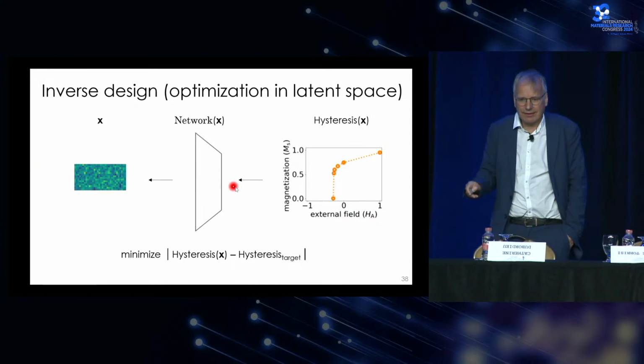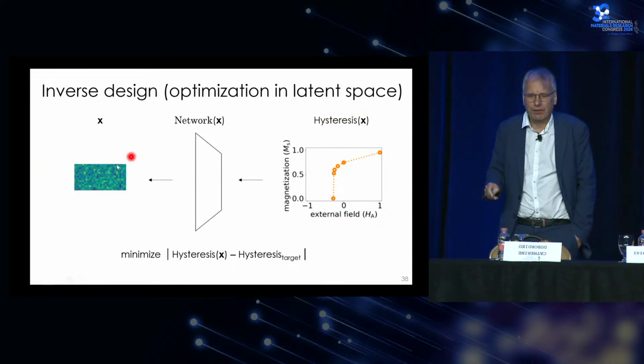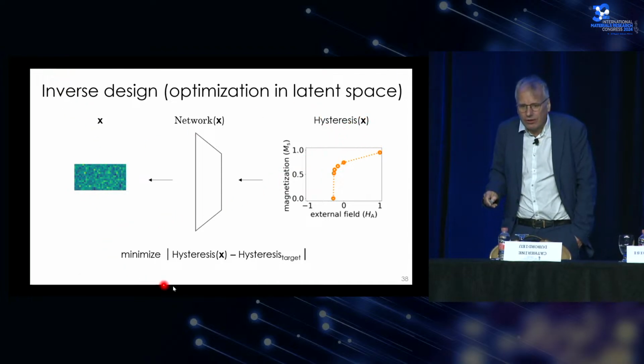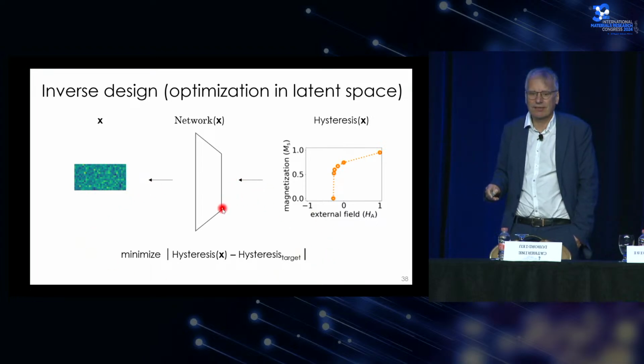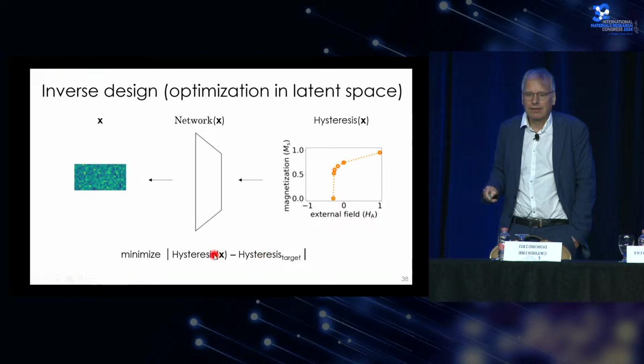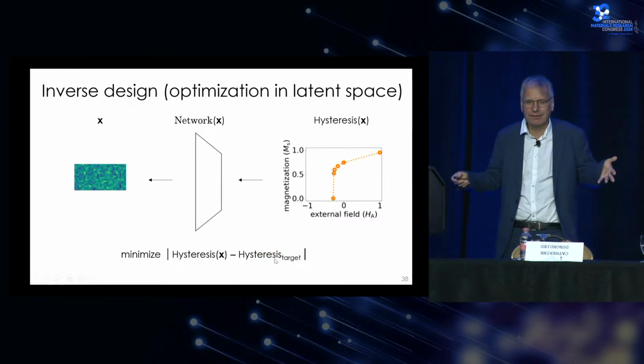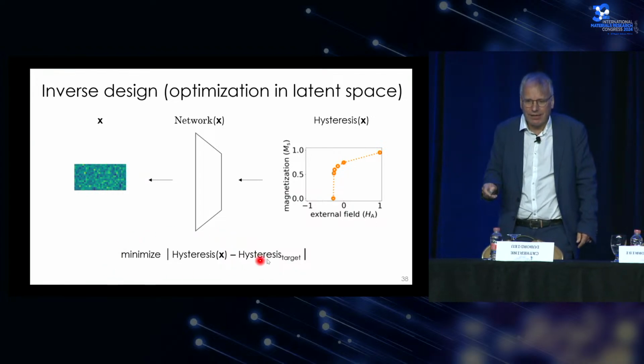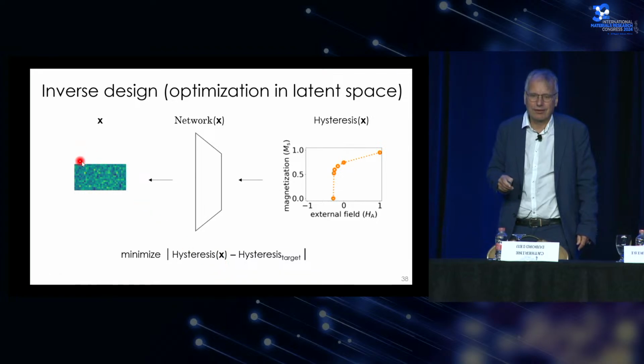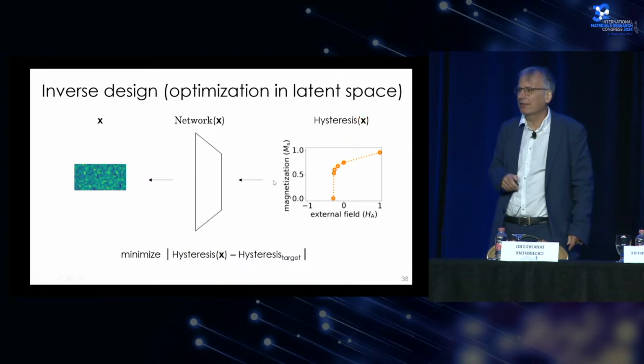Because we have this algebraic relation between the latent code and the hysteresis curve, we now can do a simple minimization task. So we want to minimize the predicted hysteresis for a certain latent code minus the hysteresis properties for a certain target magnet. And if we minimize this difference, we get the latent code for a given demagnetization curve.